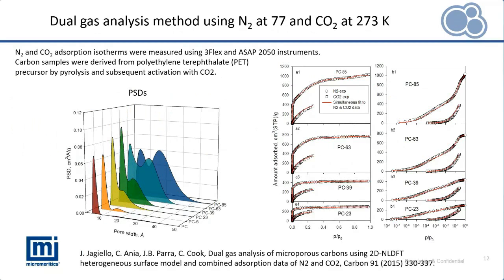It is well known that measurements of nitrogen adsorption isotherms at 77 K on microporous carbon may be extremely time-consuming, especially when the sample contains ultramicropores. Such measurements may sometimes be inaccurate when the adsorption equilibrium is difficult to reach due to very slow diffusion into such small micropores.